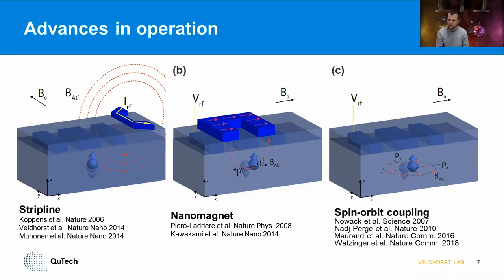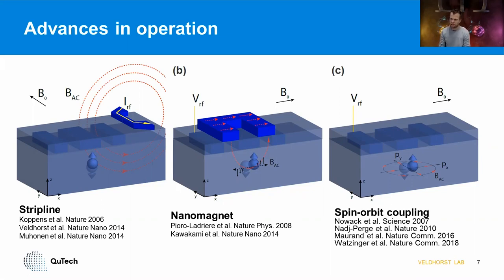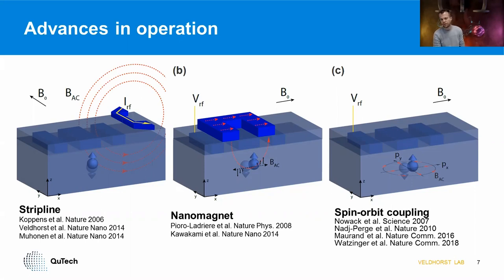There's a third option: using intrinsic spin-orbit coupling. By applying an AC electric tone, the spin-orbit coupling results in an effective AC magnetic field. This was initially used in III-V materials where spin-orbit coupling is larger. In the past four years, by switching to holes — where spin-orbit coupling is typically larger — one can use group-IV materials again. Spin-orbit-driven qubits have been demonstrated in both silicon and germanium.